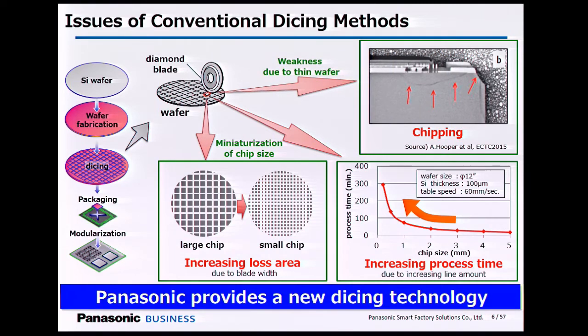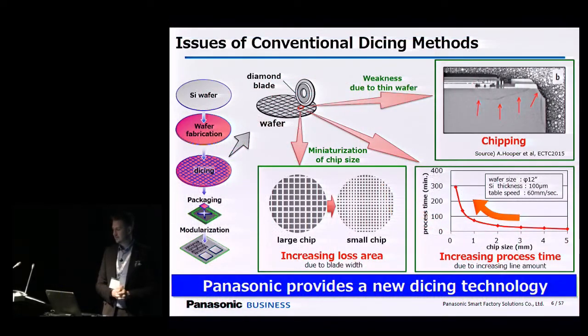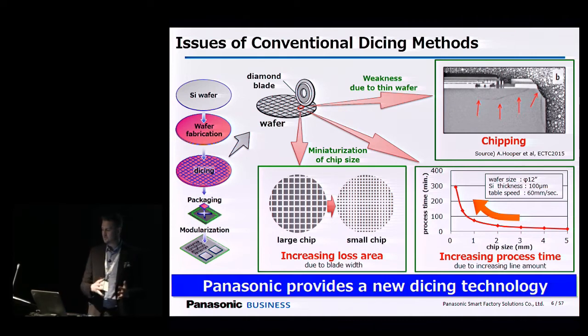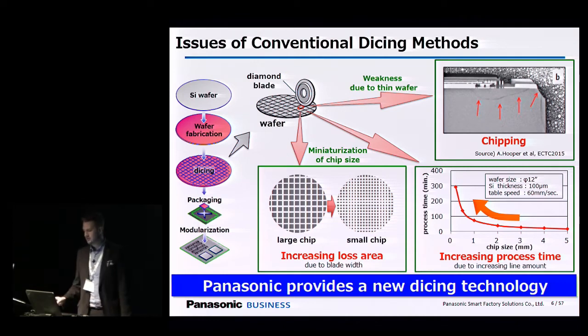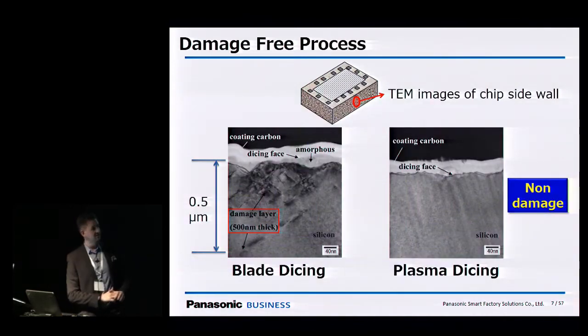So what are the issues existing at the moment? You can see in the top right, chipping again, caused by mechanical action. As in the bottom right, as devices become smaller, the process time increases because basically you need to just cut longer. And as the devices get smaller, maybe the devices start to get the same size as the blade thickness, so you're wasting wafer space. Plasma dicing can address all of those concerns.